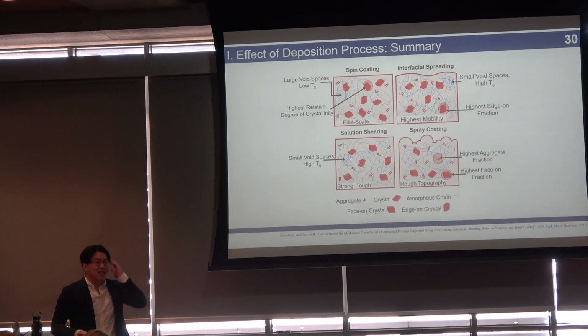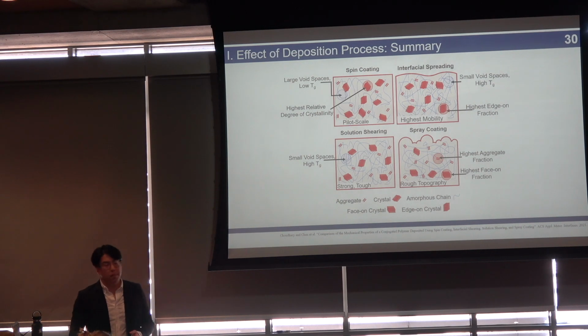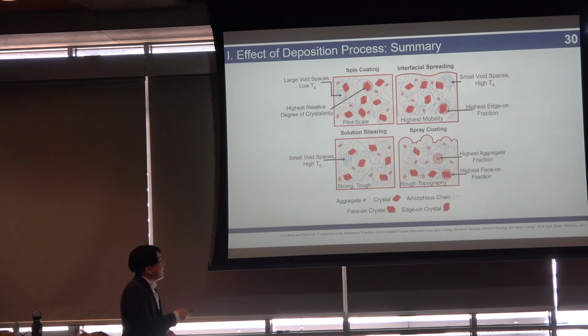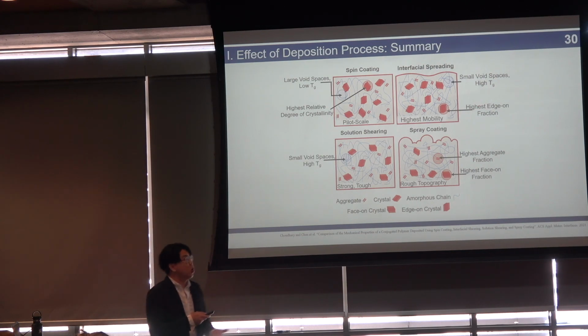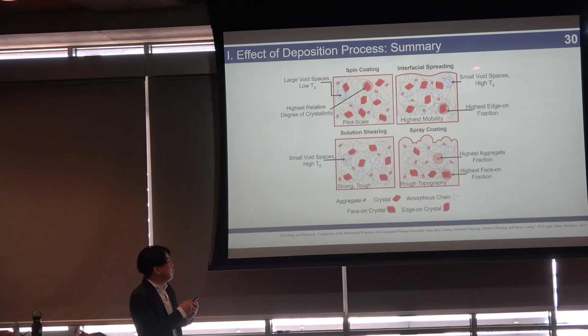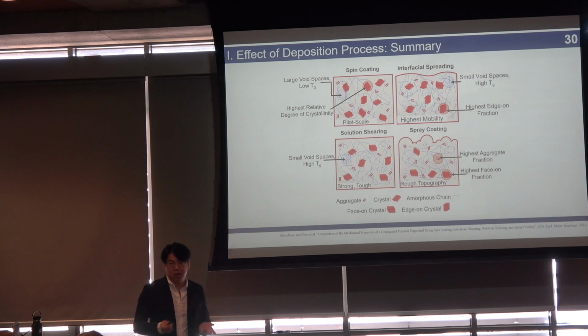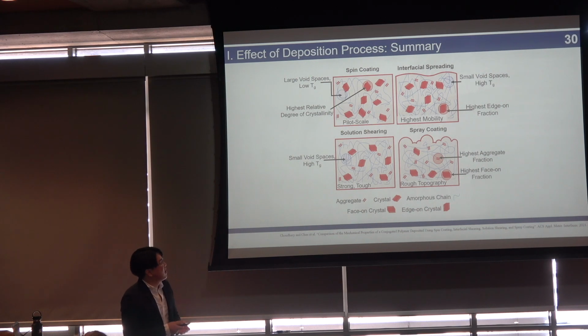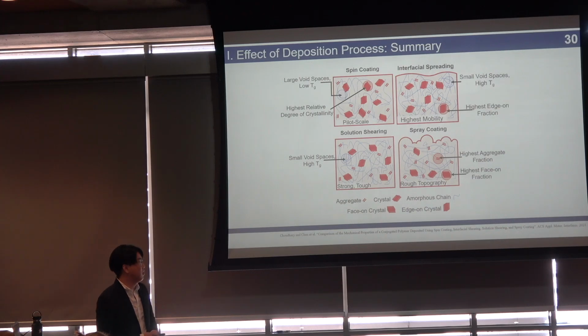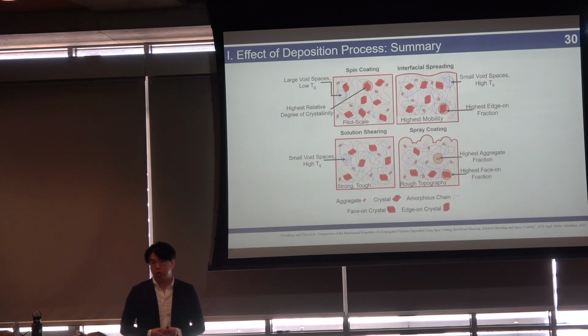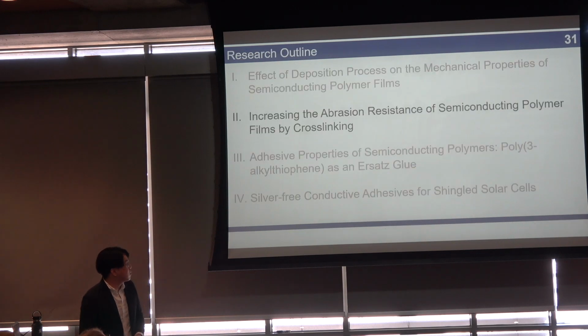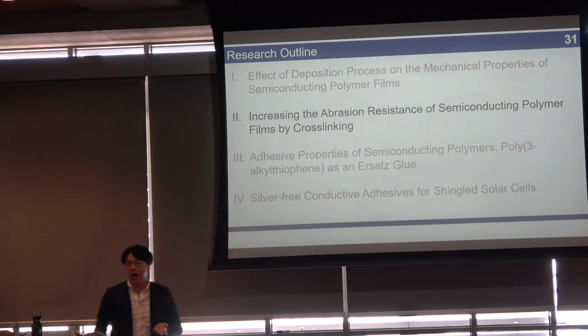So all of this analysis and characterization allows us to draw a picture of what's happening within these films. So we can attribute the good electronic mobility of solution spread films to this edge-on texturing, which leads to a very high coherence length. But very interestingly, for spray-coated films, it seems like they have pretty good mobilities compared to what we expect from their morphological characterizations, which suggests that the mobility is actually attributed to the high short-range order, as suggested by aggregation from UV-Vis. So next I want to talk about cross-linking semiconducting polymer films and why this might be useful.